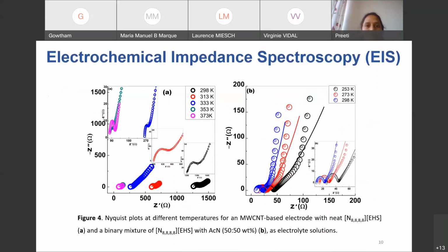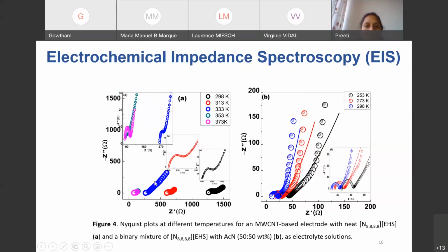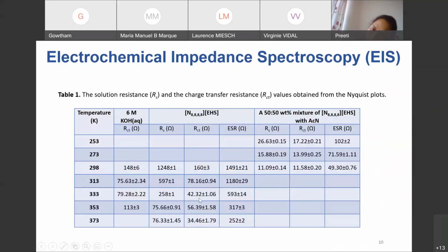Then we measured the electrochemical impedance spectroscopy of these ionic liquids, in the neat system as electrolyte and as a binary mixture. As you can see here, at lower temperature, the solution resistance and charge transfer resistance are very high for the neat solvent. But when we move toward the binary mixture, these values are very low, as we can see in the high frequency region and in the semicircles inside as well.